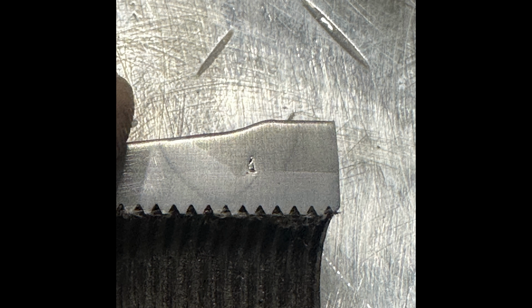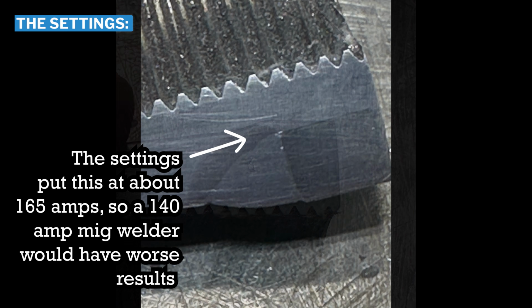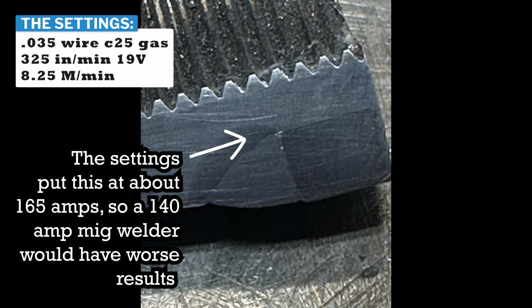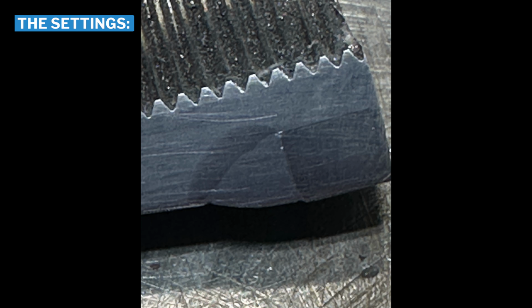All right, let's move on and look at MIG. So up first were the settings that the machine recommended for welding 3/16 material. Keep in mind the tube was 3/16, but that fitting is quite a bit thicker. So guess what? Our settings are on the colder side.